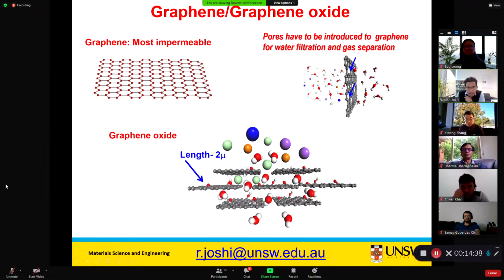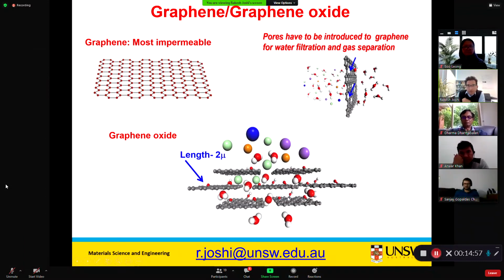These are the graphene oxide. This is, I can say, one sheet of graphene with functional groups, and the typical size is 2 micron. In the beginning we used to make 2 micron, but now we make 1 micron, even 500 nanometer. We now know that if you have smaller flakes, it's better for the water flux because you have more water inlets. So all our membranes are of this type.